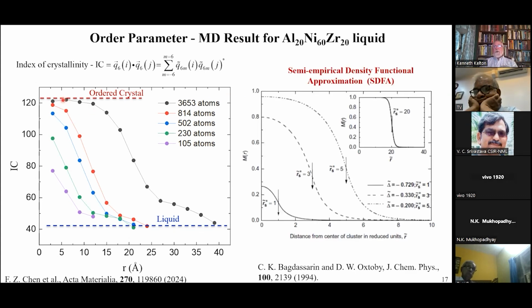These are MD simulations. These are some earlier calculations from a density functional approximation. And you see that everything here is in normalized units. So basically, as R sub S increases, you're getting a larger cluster, but they have it normalized to different things. But the key point is that as you have very small clusters, the order parameter never gets to what it should be in the crystal, which is up here. As you increase the cluster size, it gets closer and closer. And then if you get to, in their case, a very large cluster size, it still decays through the cluster because that's reflecting the diffuse interface, but at least in the center of the cluster, you have the ordered crystal. So these two are identical. And they both indicate strongly that the thermodynamic assumption in the classical theory is wrong.